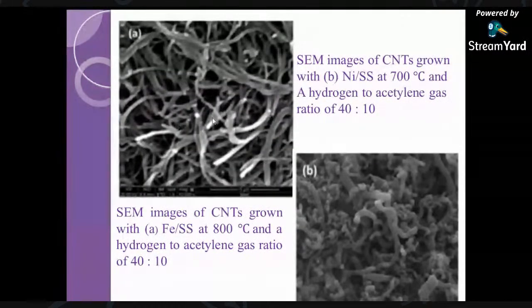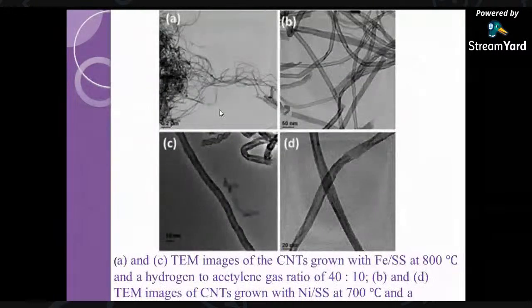Okay, so we get carbon nanotubes from stainless steel coated with catalyst layers of nickel and then iron. Here we make a comparison between carbon nanotubes grown from an iron catalyst and a nickel catalyst. We can find a difference between these two catalysts. There is a change in the morphology, the quality and the quantity of the carbon nanotubes coming out of these different catalysts. We get a good quantity and a good quality of multi-wall carbon nanotubes from the iron catalyst. And we choose this for further studies.